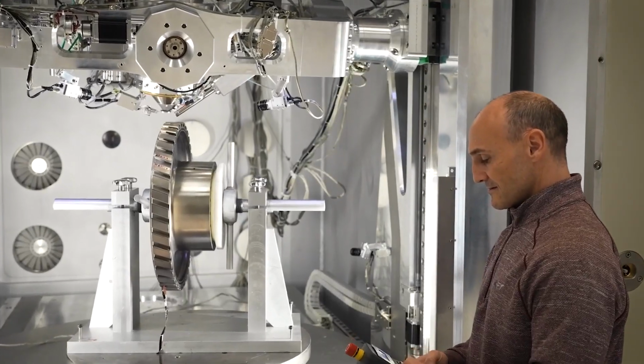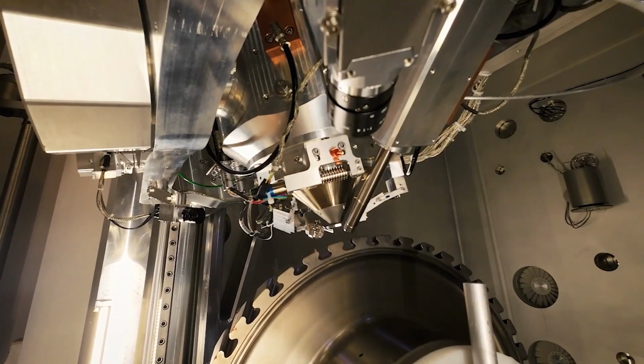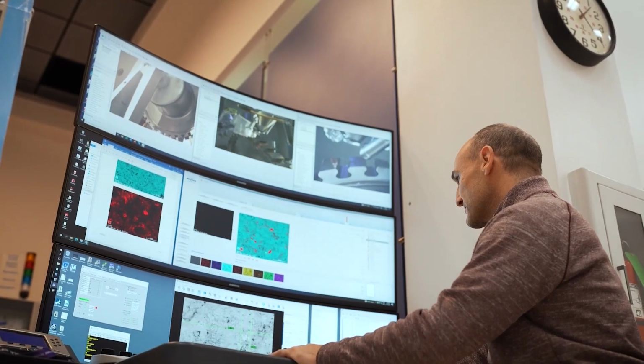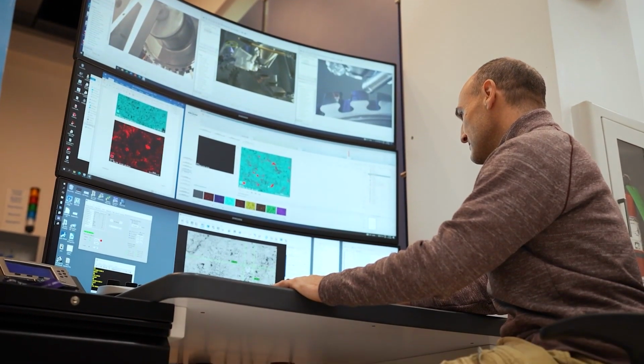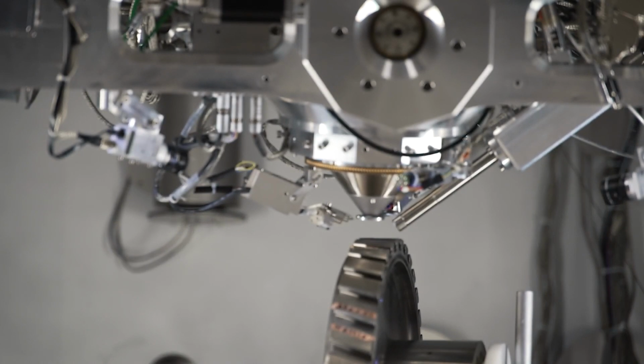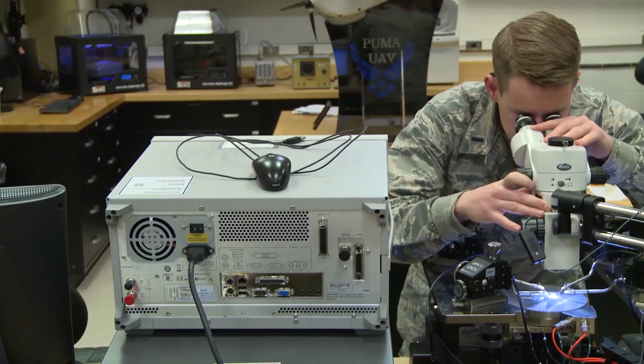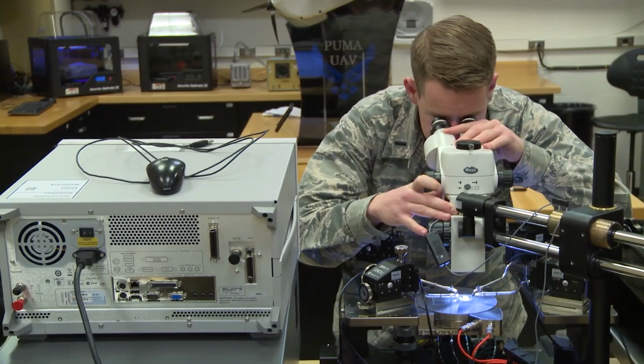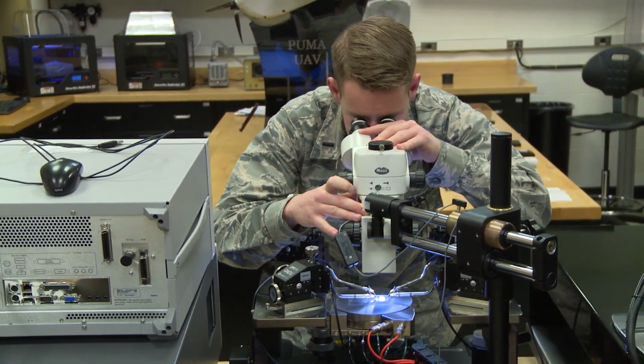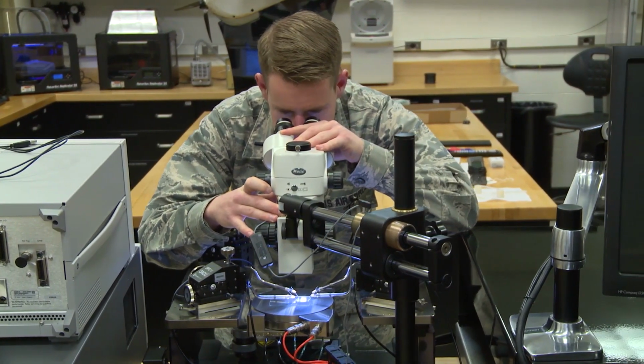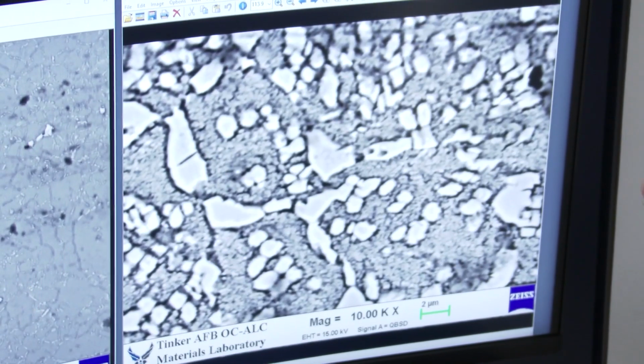Cross-sectional cuts of the substrate were taken for SEM imaging to analyze the thickness of each coating applied and to observe the effect of successive coatings layered upon one another. It was observed that the coating adhered well to the substrate surface and stacked well with one another, creating an uninterrupted layer of metal oxide. More extensive SEM imaging is in progress for us to provide some very nice and detailed images as part of this research.